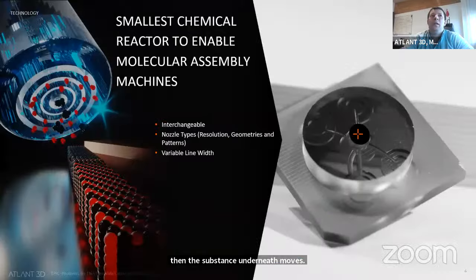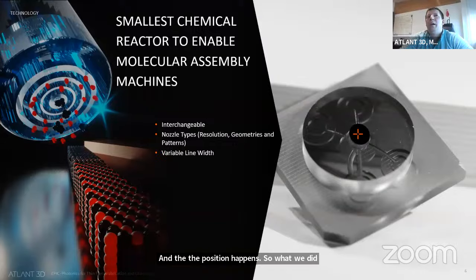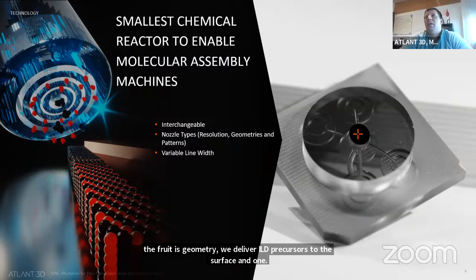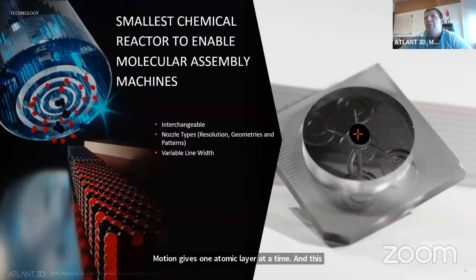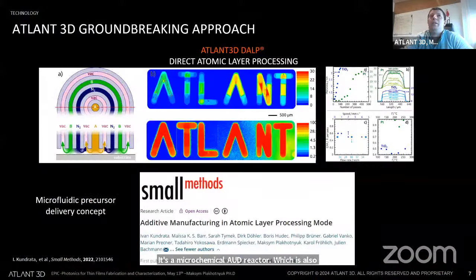So what we did, we made a micro nozzle, which has a concentric geometry, and through this geometry we deliver ALD precursors to the surface, and one motion gives one atomic layer at a time. This micro nozzle is about 16 by 16 millimeters. It's a microchemical ALD reactor, which is also replaceable. It can have different configurations of the nozzles, and the resolution provides us a local ALD process.